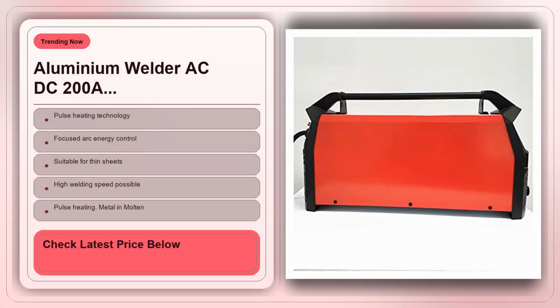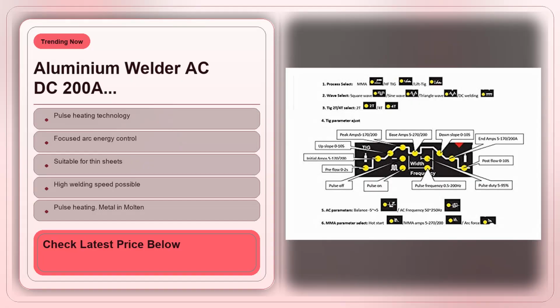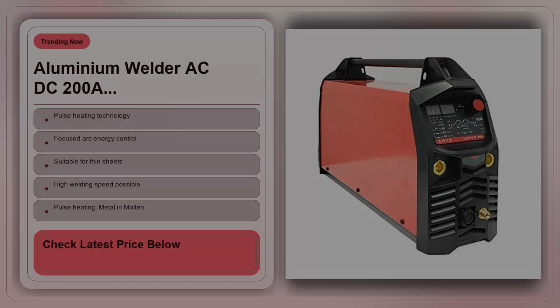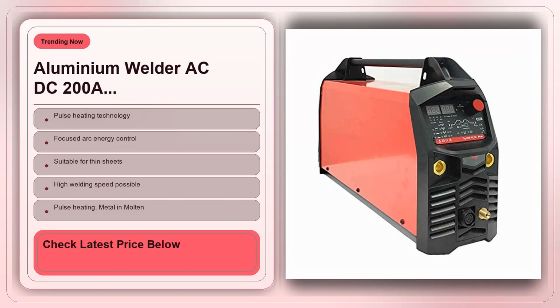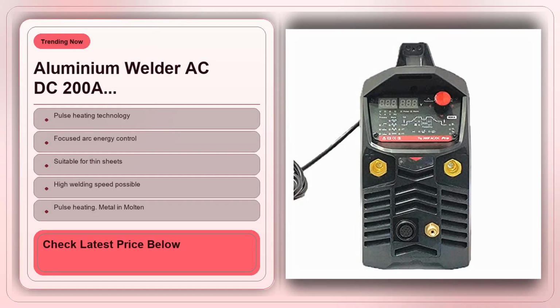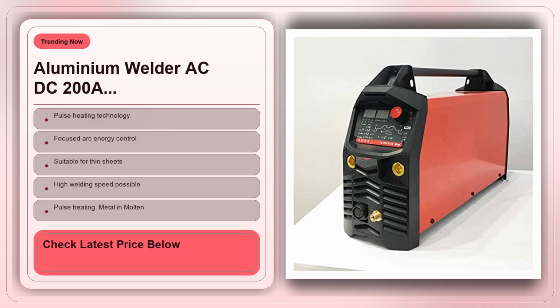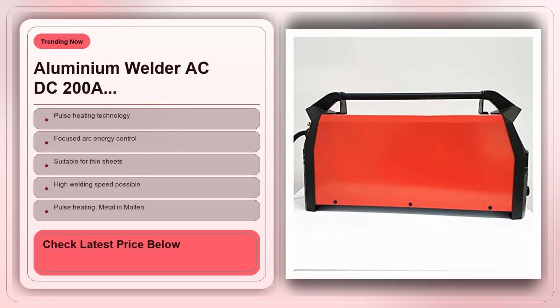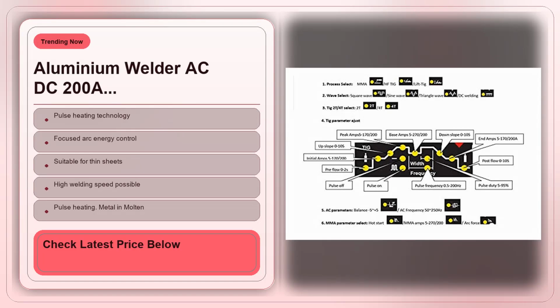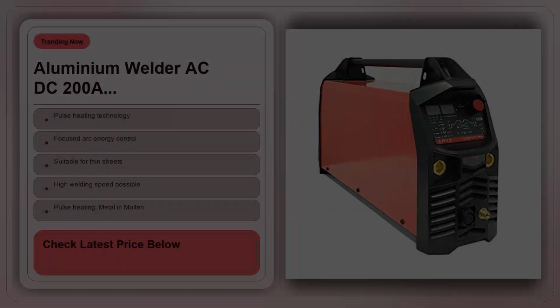Let's talk about the practical strengths that actually matter once you plug it in. First, the pulse heating function shines when you're dealing with aluminium that's only a couple of millimeters thick. By shortening the time the metal stays at peak temperature, you avoid the common problem of burn-through or excessive warping. In a real-world test I saw on a maker's channel, the operator set the pulse width to a low value, ran a 0.8 mm sheet, and got a clean, narrow bead without the usual heat-affected zone that would otherwise require a second pass to clean up. That translates into material savings and less post-weld machining.